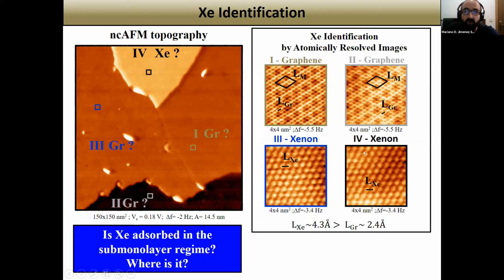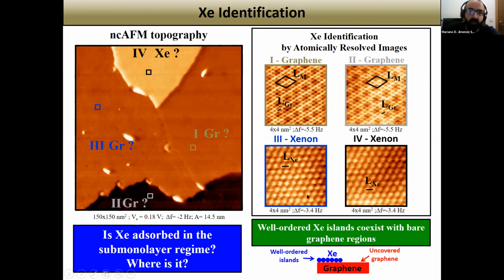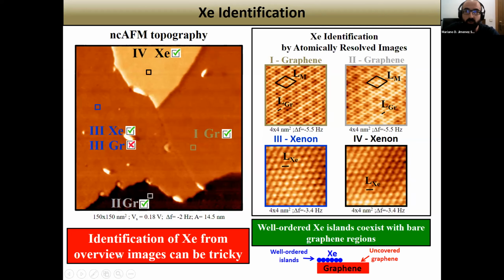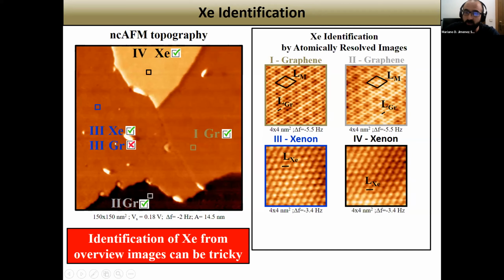And what can we learn from here? Well, we can learn that we have well-ordered xenon islands on the surface which present a hexagonal structure that coexists with bare graphene regions. And one more, well, we can also see that the identification of xenon from overview images can be tricky. I mean, here we were wrong. Of course, we can always employ atomically resolved images to distinguish, but there are some drawbacks, like that not all tips can achieve this kind of resolution, and that this is a time-consuming process.